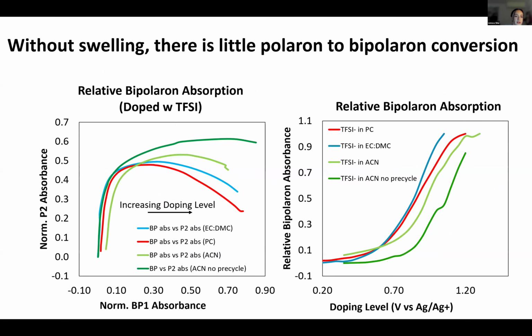Okay. So I also plotted the P2 peak versus the BP1 peak. And we can see that the more swelling the solvent is, here's red, which is propylene carbonate, the more we see P2 diminish as BP1 gets to higher values. And our P2 diminishes less, the less swelling the solvent is. And then when we don't pre-cycle the film at all, we see very little P2 diminishing. And then if we look at the bipolaron absorbance as well, we see this entire curve is shifted to the right, or higher potentials, indicating that it's more resistant to forming bipolarons when it's not swollen.